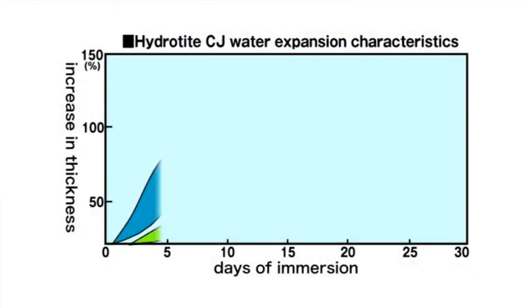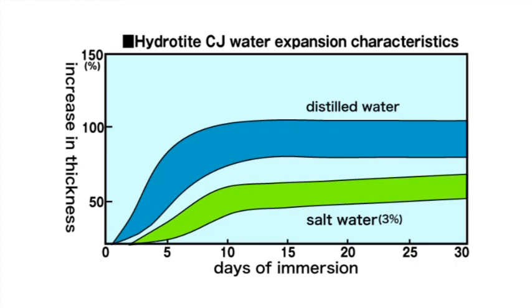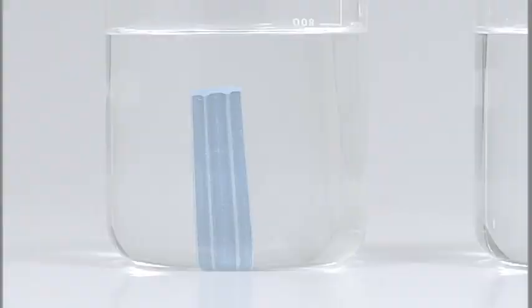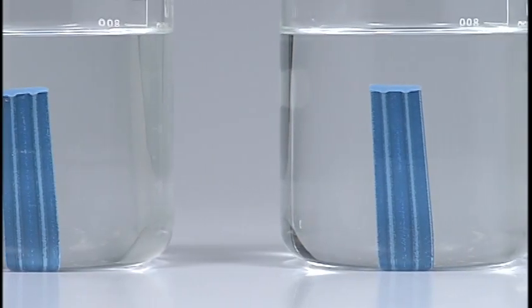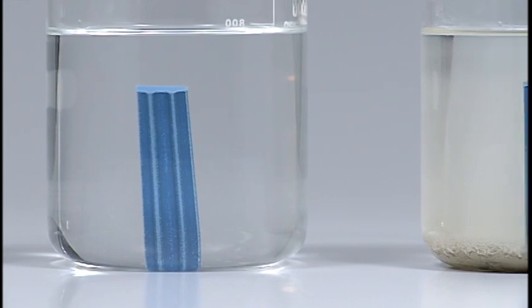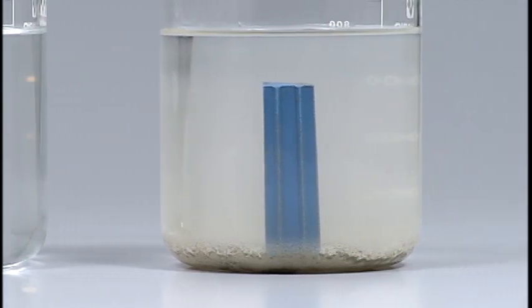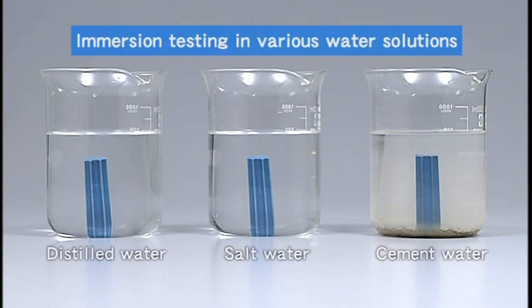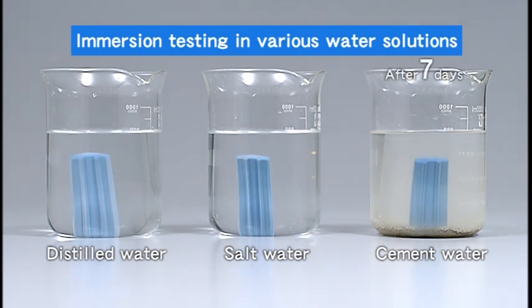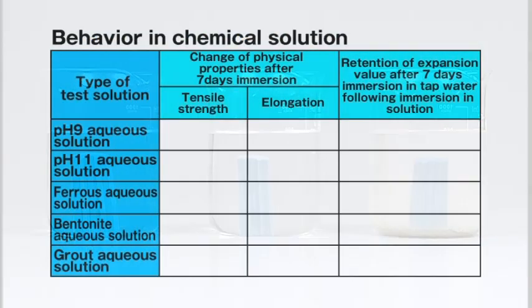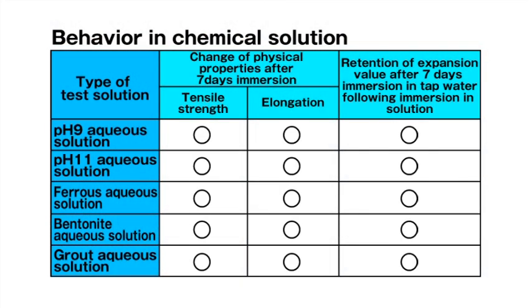The graph shows changes over time in the thickness expansion increase rate following immersion in distilled water and salt water. Hydrotite carries out these functions in a variety of environments. The characteristics of test materials were compared upon 7 days immersion in distilled water and various other solutions. Hydrotite maintained its expansion performance in all solutions.